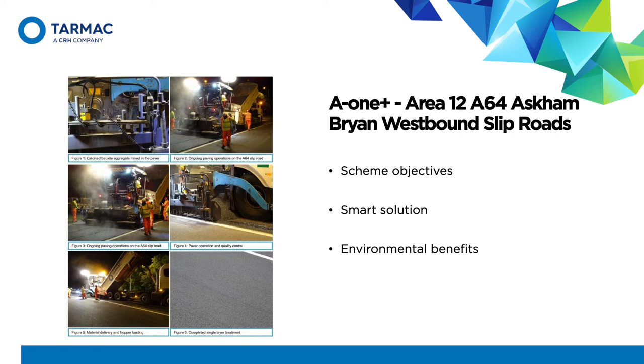We developed a scheme to replace the existing high-friction surfacing with 2,450 square metres of a single layer of ULTIGRIP surface laid at 40mm depth. The environmental benefits that were delivered were: traditional high-friction surface course can often fail to deliver expected long-term performance in terms of durability and longevity, with experience showing that replacement can be every 2 to 3 years to maintain performance at high-risk sites. This regular replacement cycle can also damage the underlying asphalt surface, which may require replacement earlier than would normally be expected.